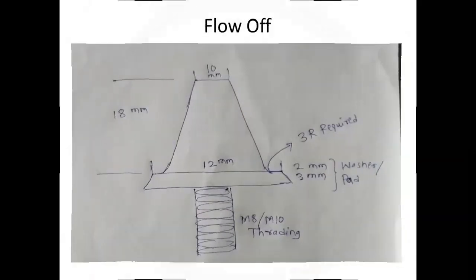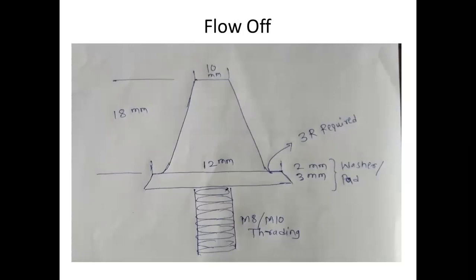Next. This sketch is purposely given because of the flow-offs, basically. Rejection due to sand. While doing the molding, if you can see clearly, I have provided 3R required. Then diameter of flow-up at top 10 mm, at bottom 12 mm. Thickness of pad 2 mm, washer, then M8 or M10 tapping. Because these are minor things, but most important. Otherwise, if the flow-up is bent, then mold breakage will be there, extra sand will be there. That has to be ground, or that sand may fall on the casting surface after closing or while clamping the box. That's why